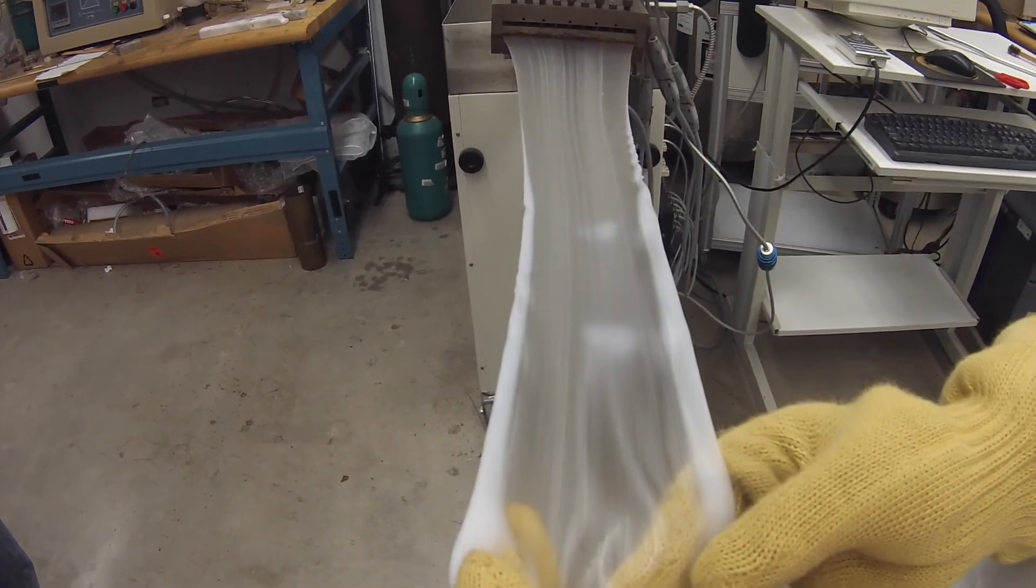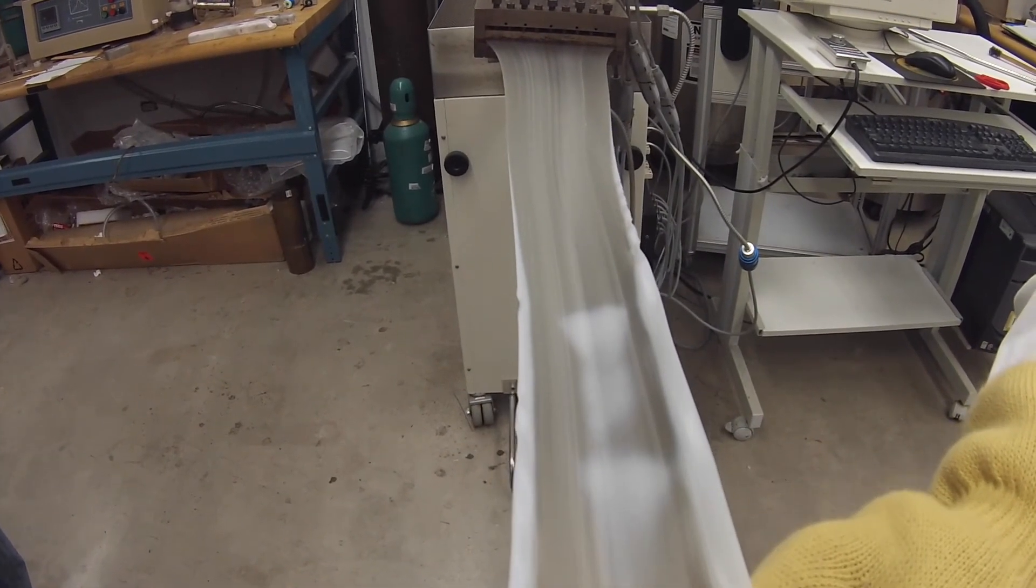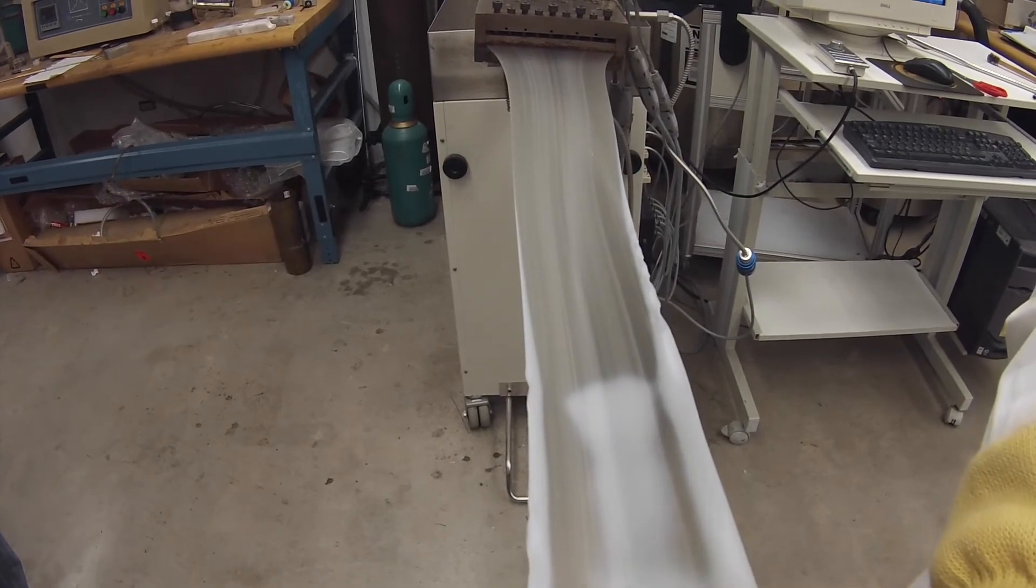As we continue with the stretching, see how the cold front advances. It basically starts becoming opaque. There's internal order.